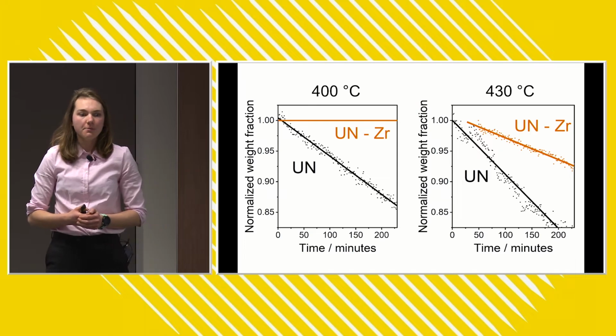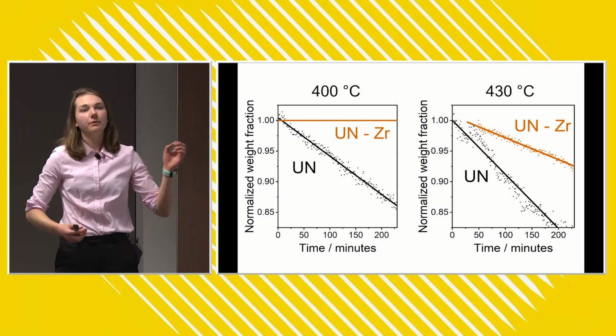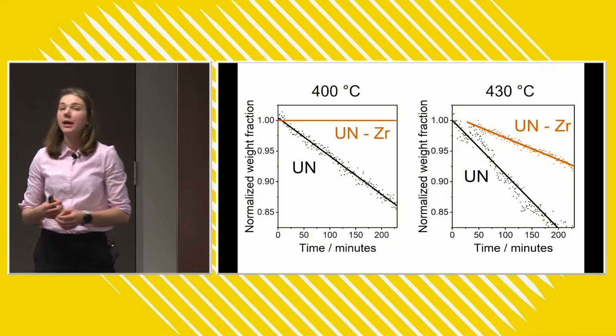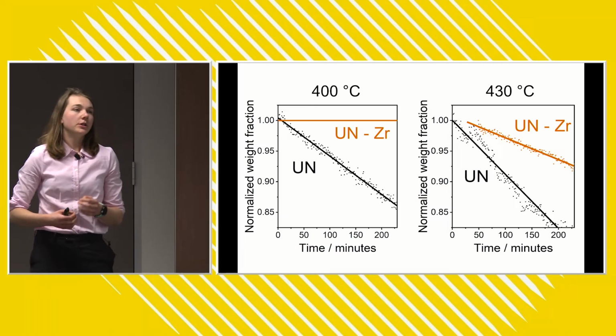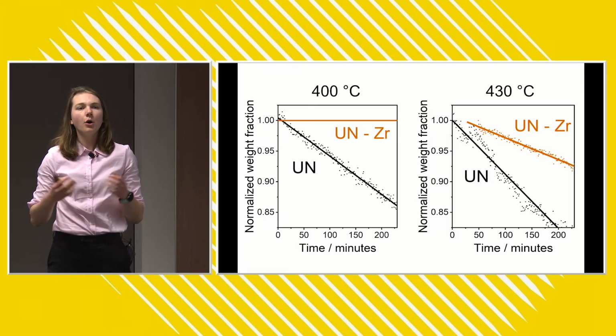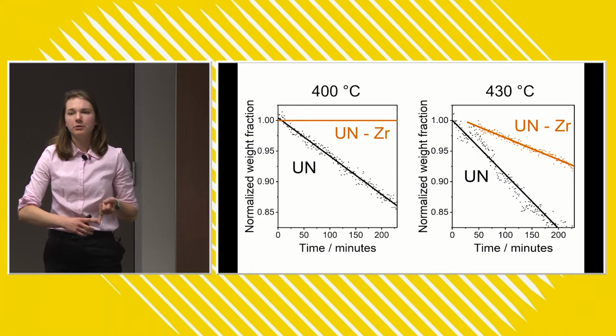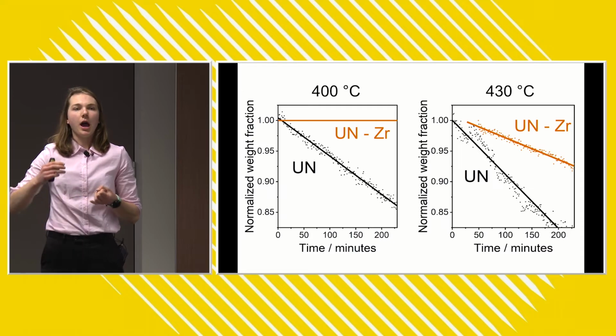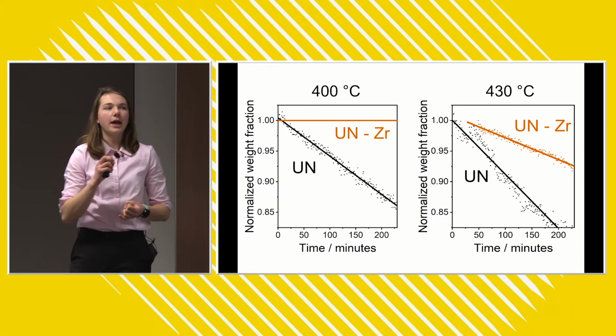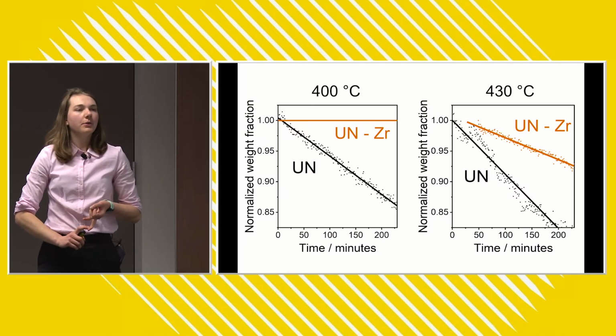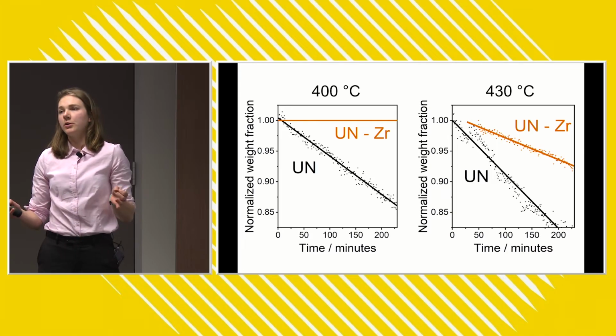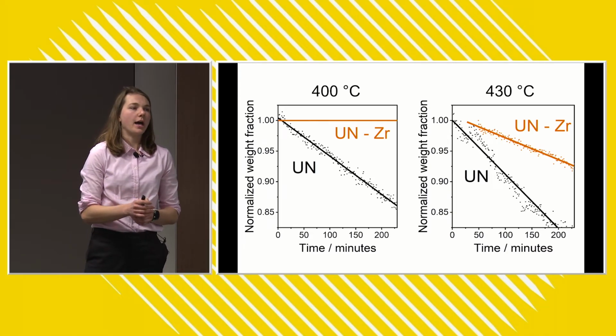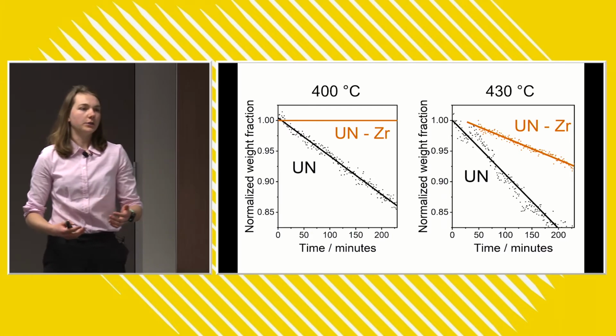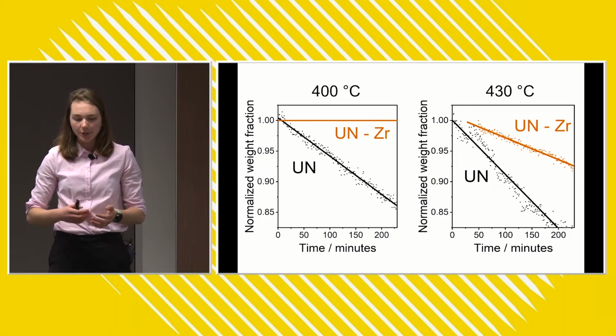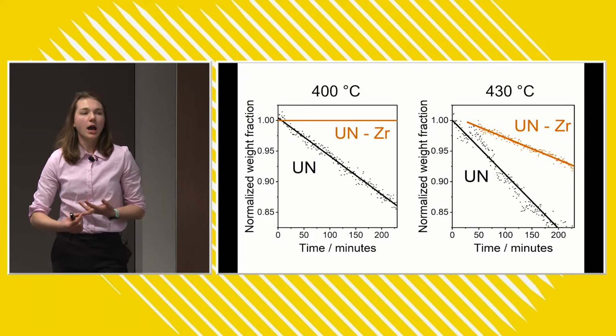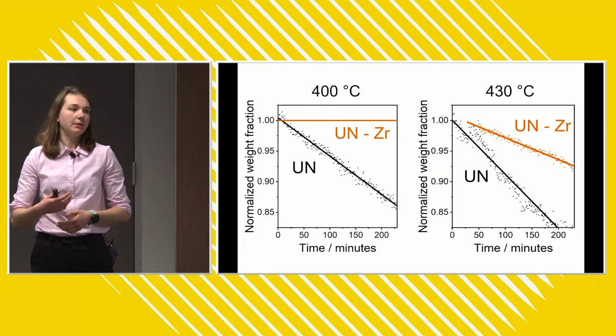So where next? We've identified that we can improve the corrosion properties of uranium nitride fuel by adding zirconium. What we then want to do next is see, well, if the whole point of this uranium nitride fuel is that it's higher density than the uranium dioxide that's currently used, how little zirconium do we need to add to still get those benefits? Another area that we're going to explore as well is how do the corrosion processes change to a fuel that has been in a reactor for, say, 3-4 years already? Is that going to be the same? And we can do that by simulating the fuel having been in the reactor by doping it with elements such as molybdenum and niobium.